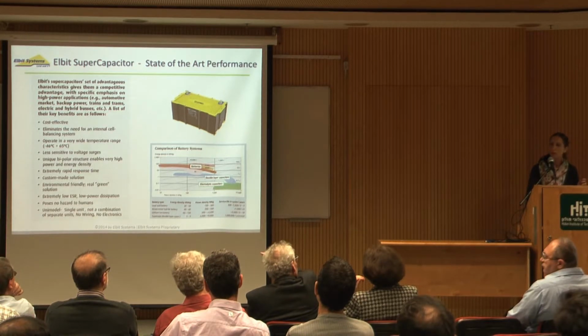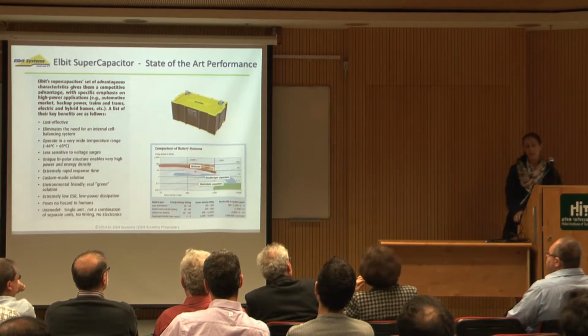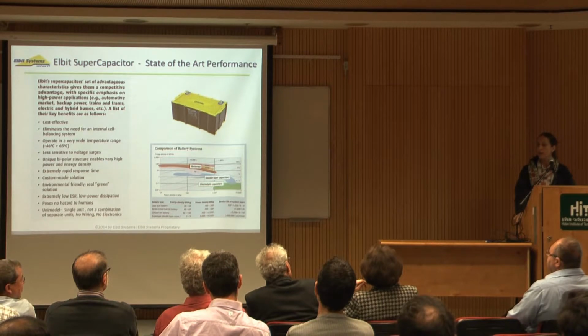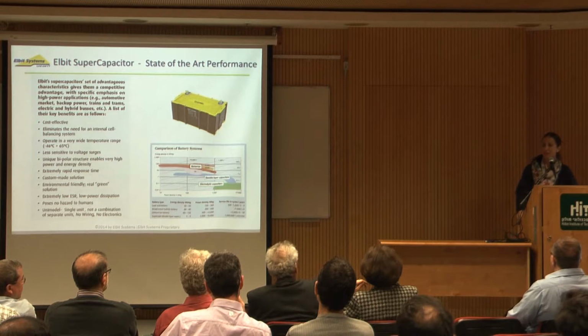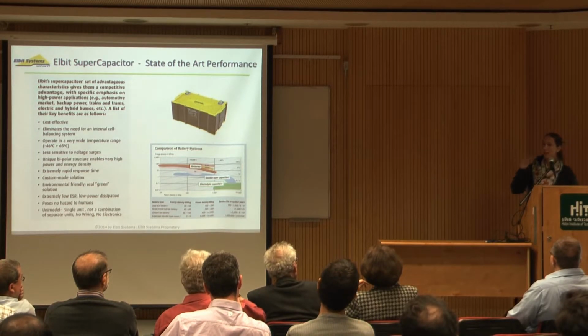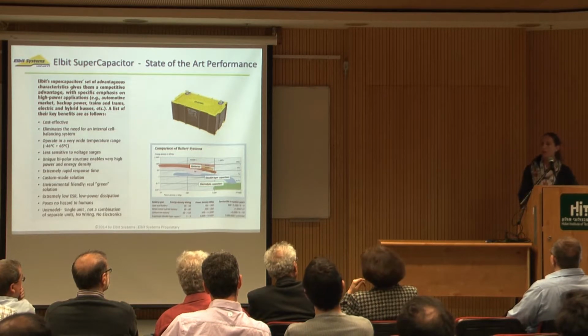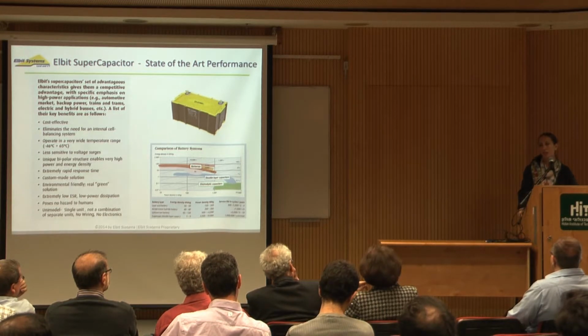How do you get to -46 with an aqueous solution? With aqueous, actually, we are using a certain concentration of the alkaline solution, which is fitted to the phase diagrams, and the freezing point of that specific concentration is beyond -50. But it has to be at the specific molarity. Once you deviate by only, let's say, 5% in either direction, then you will not achieve that